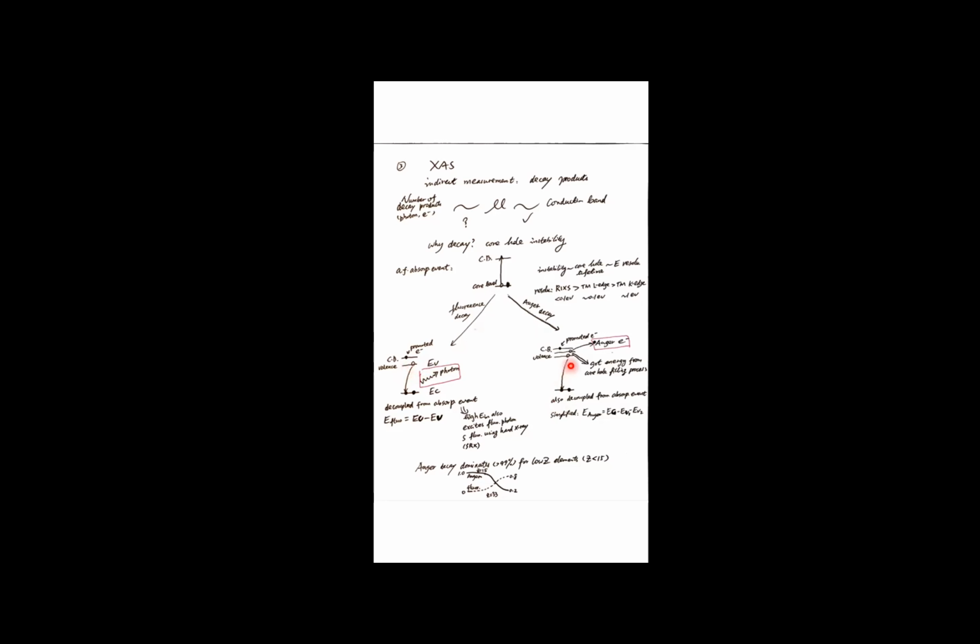But what happens next is, instead of emitting a photon that takes up all the energy difference, it actually gives all this energy difference to another valence electron. They may not be in the same orbital, by the way. But this system gives this energy difference to this electron that is originally already there in the valence orbital. And this electron, after absorbing this energy, goes out as a free electron with kinetic energy. And this is the Auger electron. This electron comes from the original system.